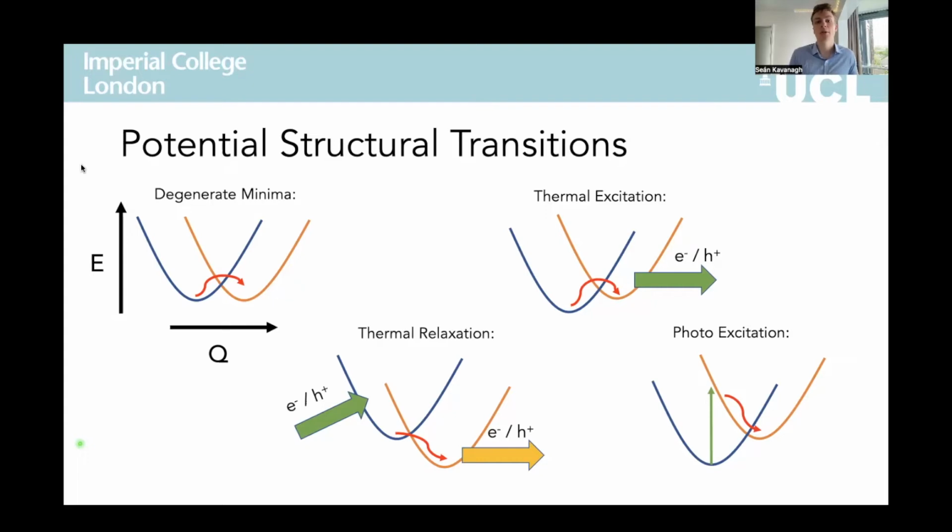For example, electron paramagnetic resonance measurements, which can give really detailed characterization of point defects, are typically performed at near 0 Kelvin temperatures, and so would be likely to only show the symmetry broken anisotropic defect states. Whereas under room temperature operating conditions, such as DLTS, for example, the defect may be hopping between equivalent structures much faster than the experimental timescale, behaving effectively as an isotropic species.